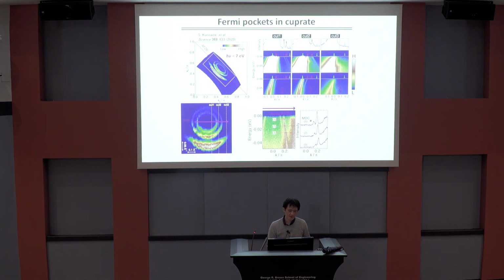This is the most important result. We found two small pockets rather than the famous Fermi arc. This is the dispersion along cuts 1, 2, 3, and you can clearly see the dispersion on the backside of the Brillouin zone about this antiferro zone boundary. For the Fermi arc, there is no counterpart.